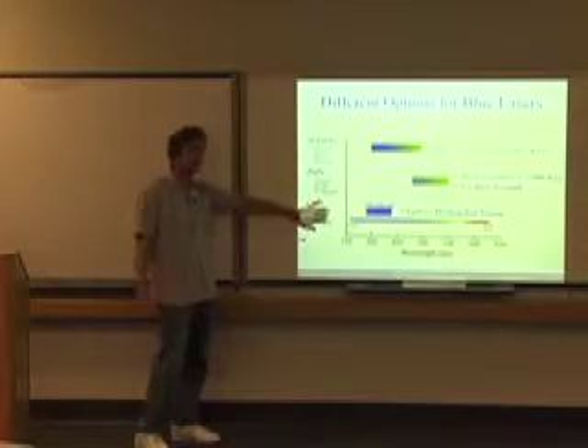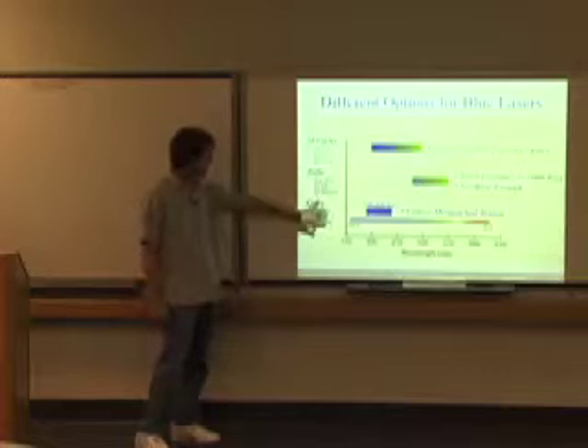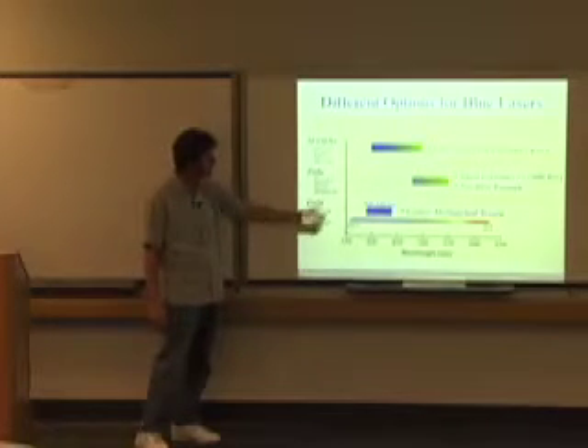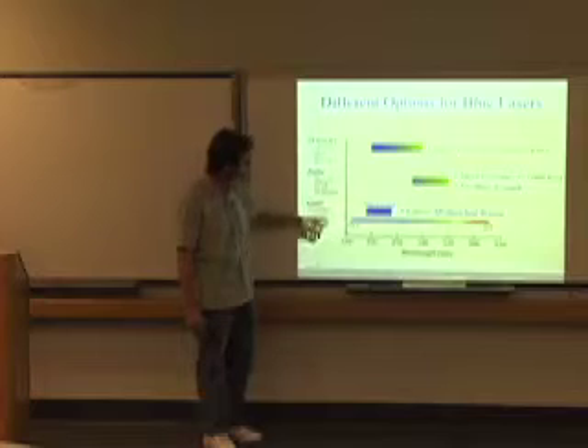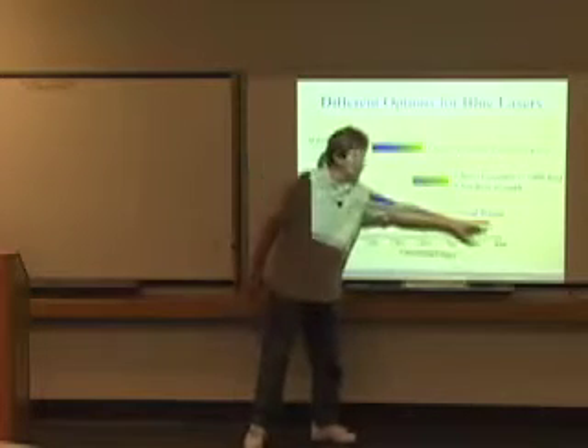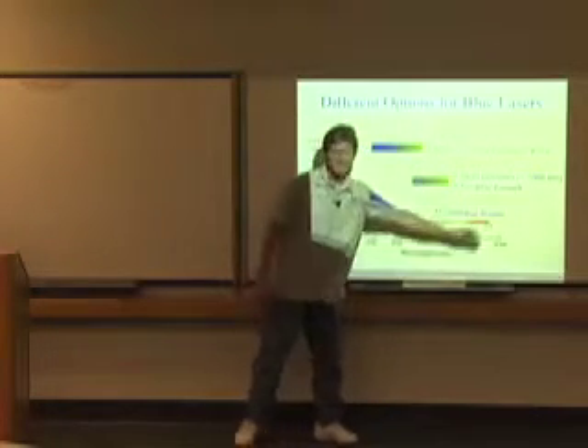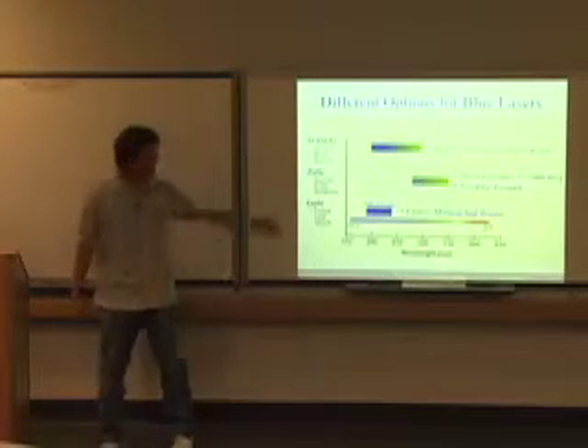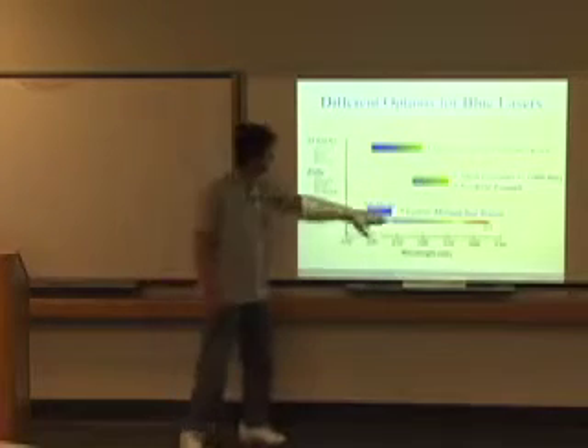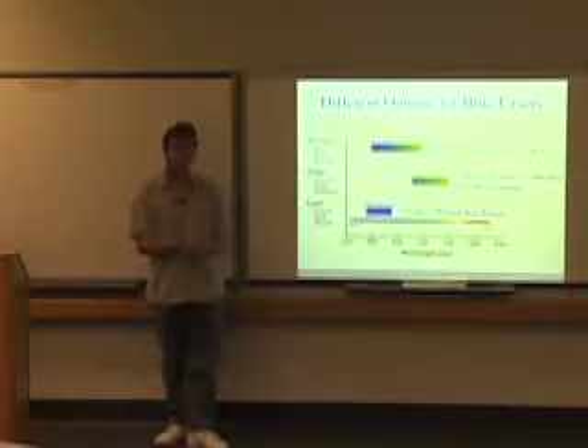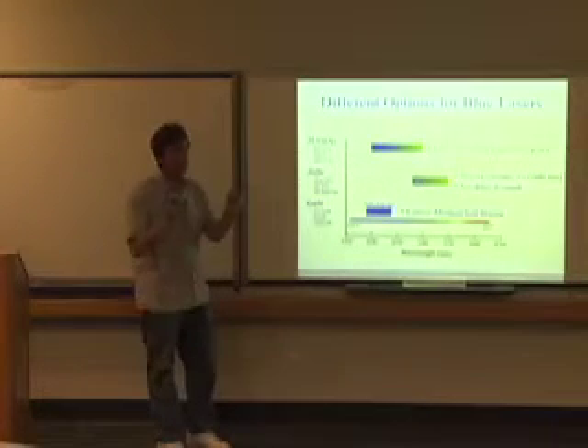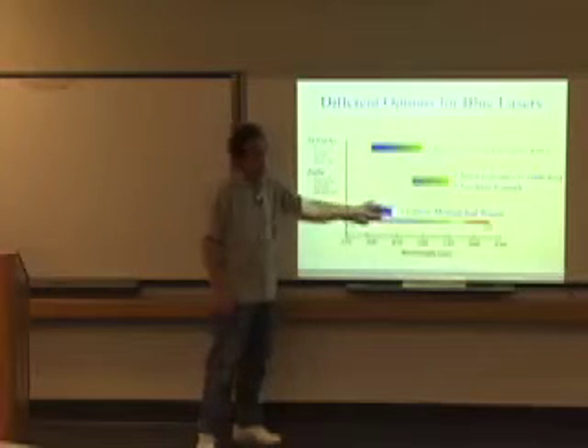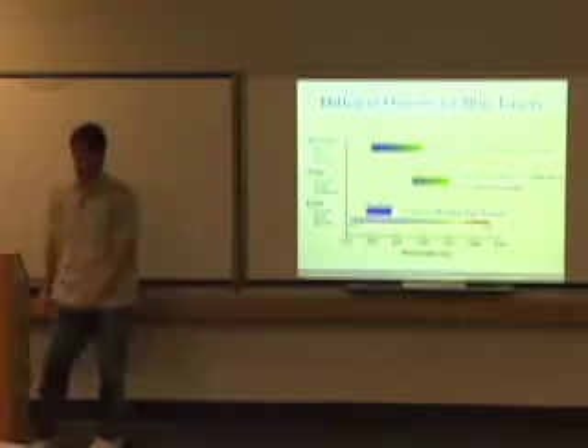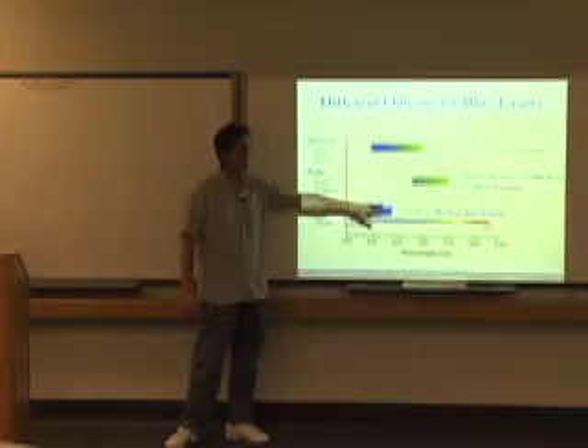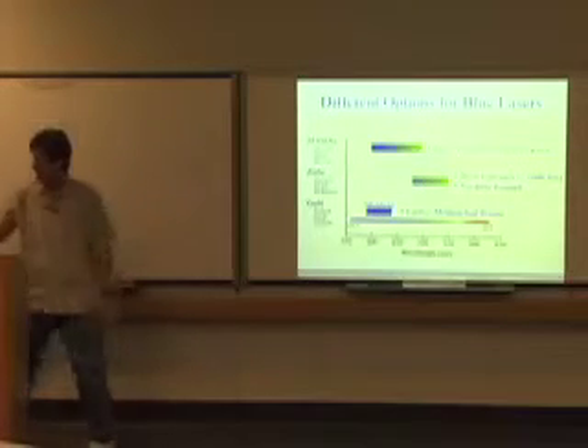And then gallium nitride seemed very attractive. So there was a lot of success in the LED work, and so making lasers out of the same material seemed very, very interesting. In particular, if you look at gallium nitride bandgap all the way to indium nitride bandgap, it spans pretty much most of the visible spectrum, which of course is why LEDs are of much interest for gallium nitride, but lasers as well. But for DVDs and for Blu-ray discs and things like that we know of now, you're really more interested in the bluer side, the shortest wavelength you can reach. And so blue, especially in the 400 nanometer range for gallium nitride, was kind of a sweet spot for what people were interested in.